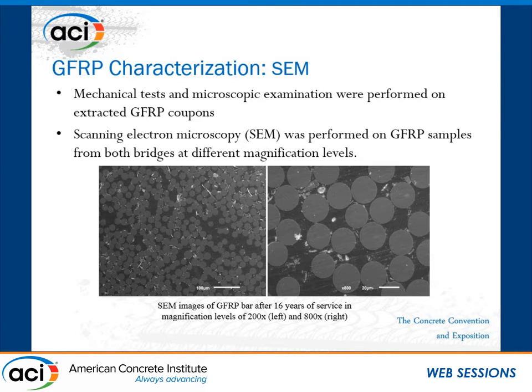Scanning electron microscopy was performed, and the main purpose was to look into even a single fiber level to see what has happened to the microstructure of these composite materials. As you can see here in this picture, this is the SEM at 2 different magnification levels. I need to say that we have performed the SEM for several samples and for several random locations, and here I'm presenting only representative samples.